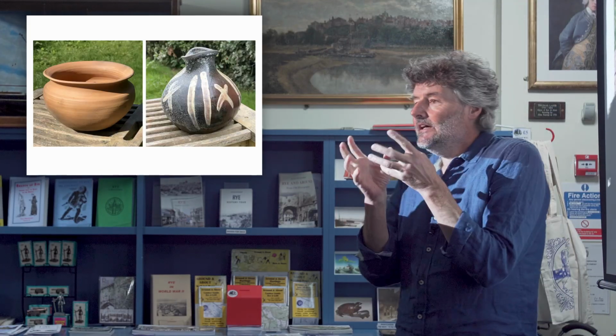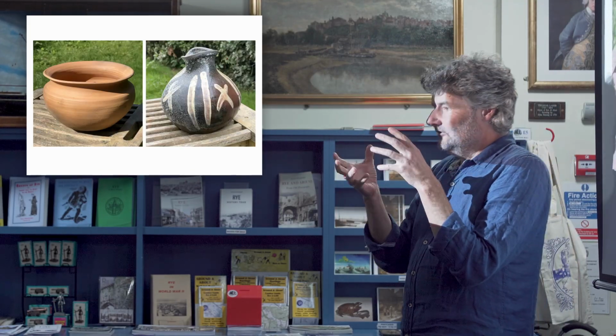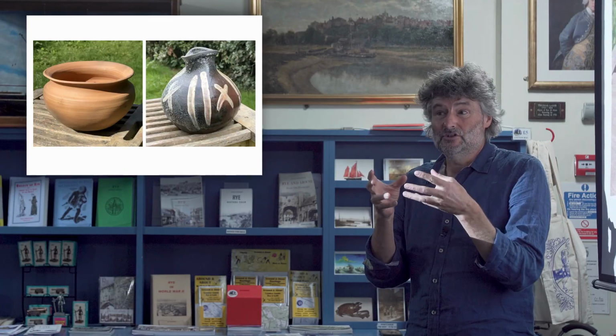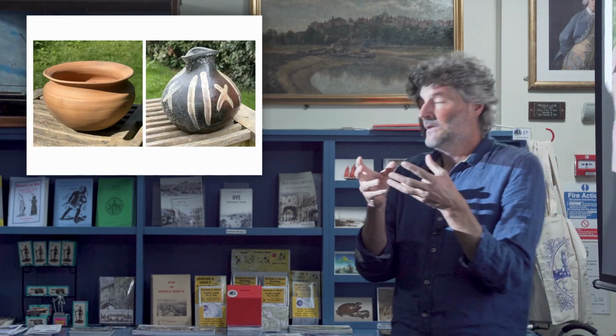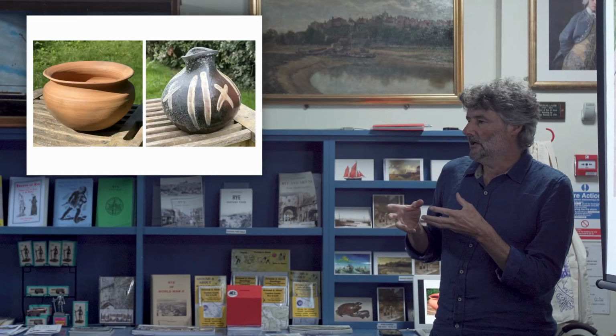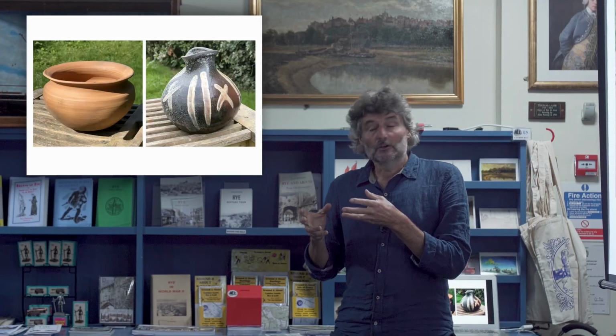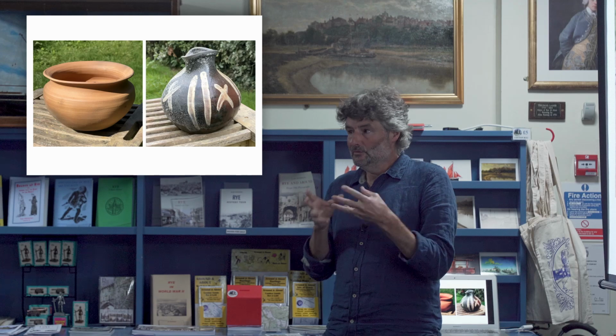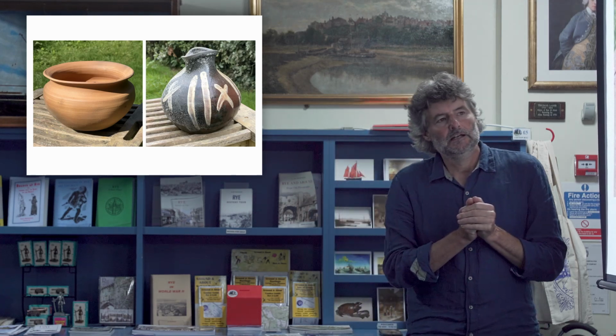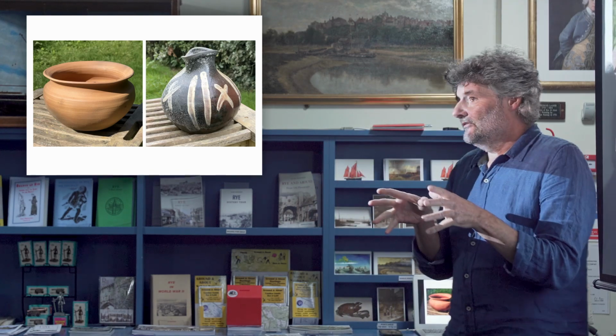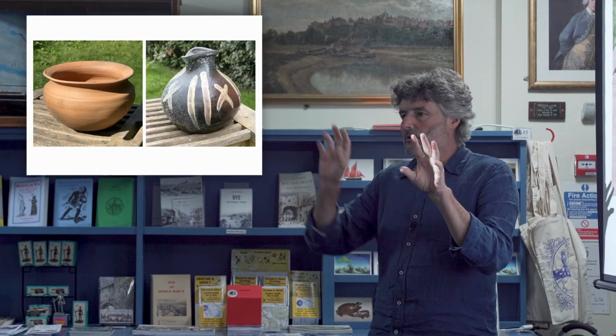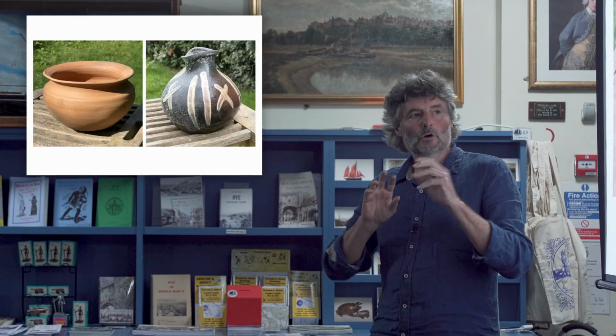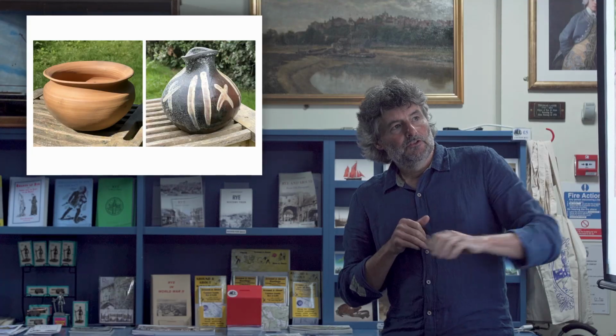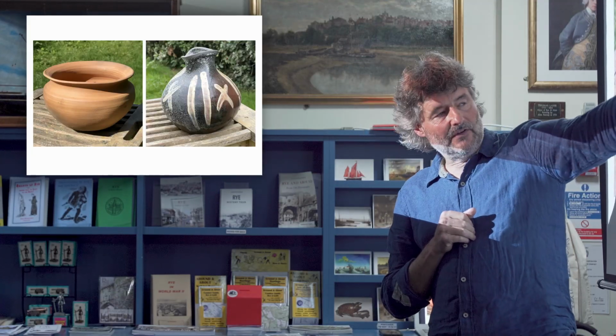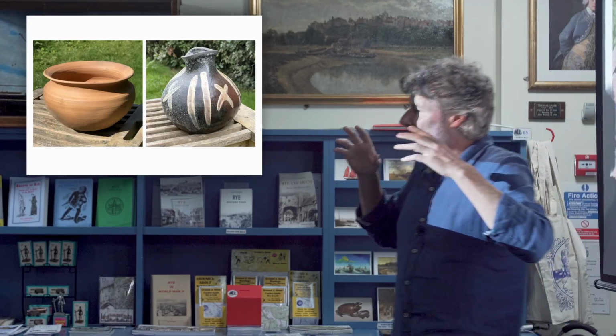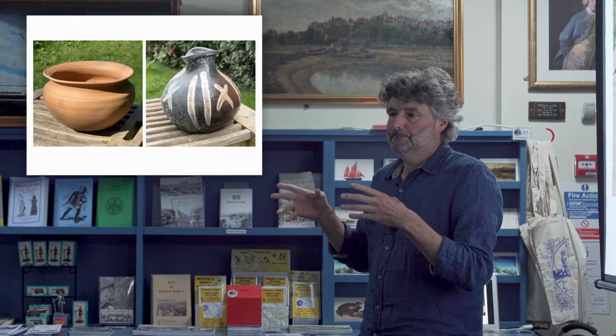The clay has started to melt, it's started to soften. So we've actually got it to a temperature beyond where it should be. And we think a lot of the failures we had were because actually the kiln got too hot. In a sense, we were too enthusiastic or too successful. Parts of it, at least. So it may be that the places where we were monitoring the temperature were different from other parts of the kiln. So much of what we see in the failures are the sort of symptoms of overfiring.